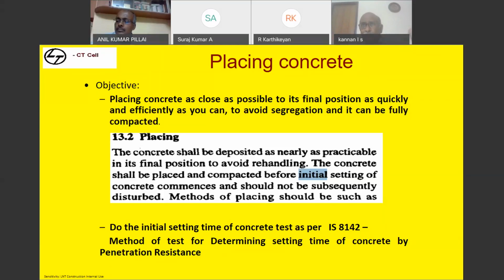Why I want to say this is, many specifications correlate with the ambient temperature. If the ambient temperature is 20 degrees or less, the concrete can be placed up to 90 minutes. If it is more than 20 degrees, within 45 minutes or 30 minutes concrete needs to be placed, which is a highly impracticable condition. Reason is, even when the concrete is mixed in a batching plant and delivered to the site, that itself takes around half an hour to 40 minutes. So within 40 minutes after the addition of water, concrete definitely cannot reach site.